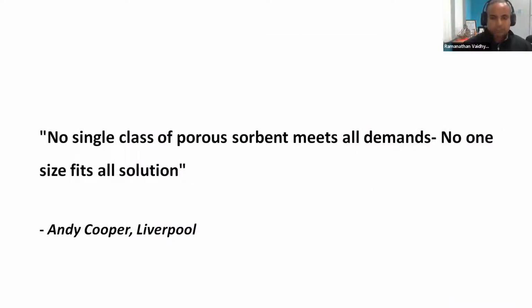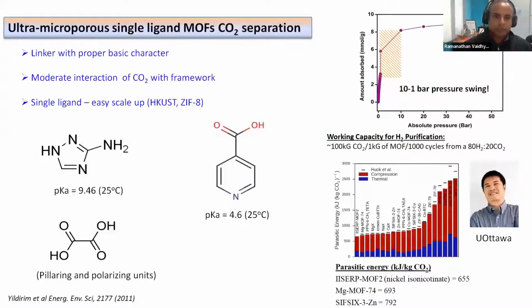There's a very nice philosophy proposed by Professor Andy Cooper, and we follow it: there is no single solution that can solve all the problems. For example, in terms of MOFs, we work on preparing what are called ultramicroporous MOFs using single ligands, so that it is potentially easier to scale up. We look at these MOFs for various CO2 capture applications in general. You can see some of the ligands we use shown here. These typically tend to form nice ultramicroporous MOFs.